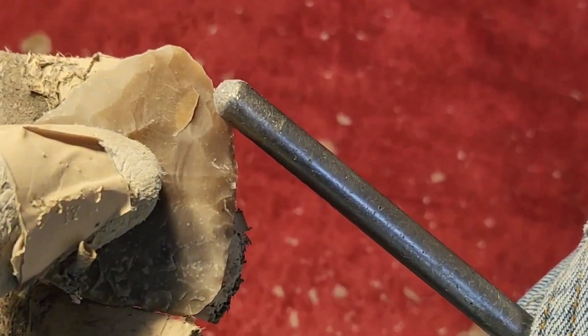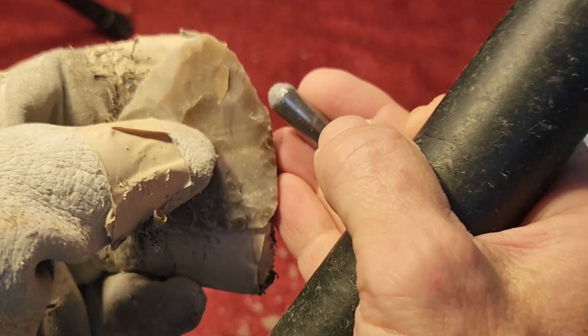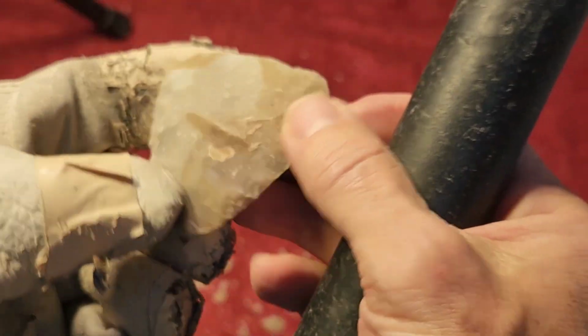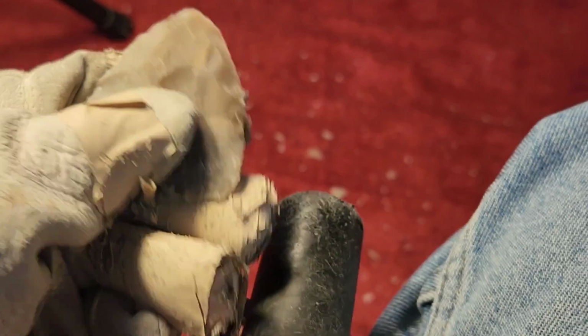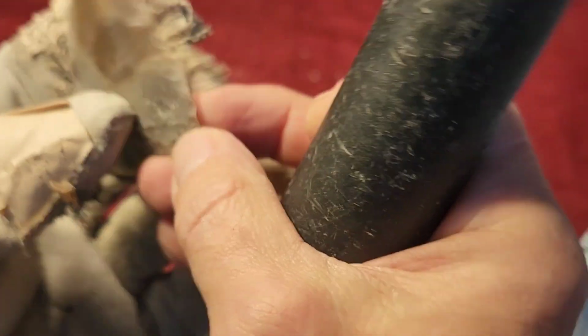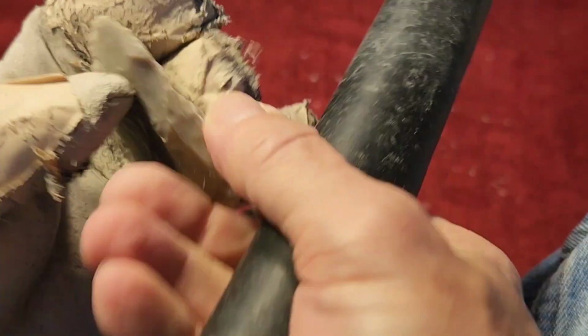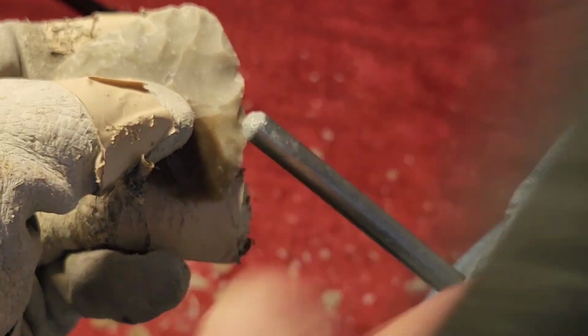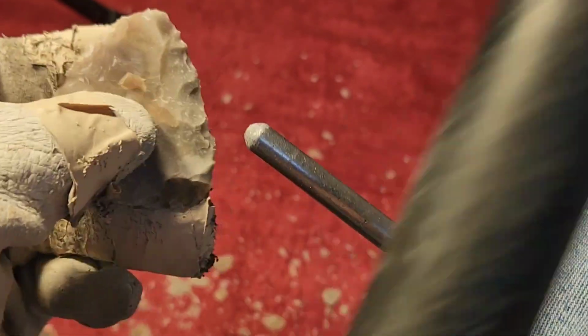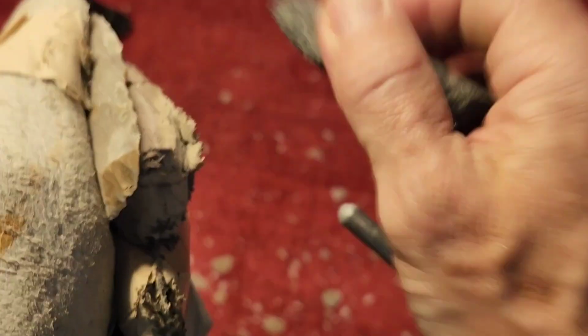You can heat it and cool it down many times without worrying about ruining the stone, as long as it doesn't get too hot. If it gets too hot, it breaks up in the kiln, turkey roaster, campfire, or whatever you're using, or it becomes too brittle to knap easily. You can still knap it when it's really brittle, but it starts to give you diminishing returns.